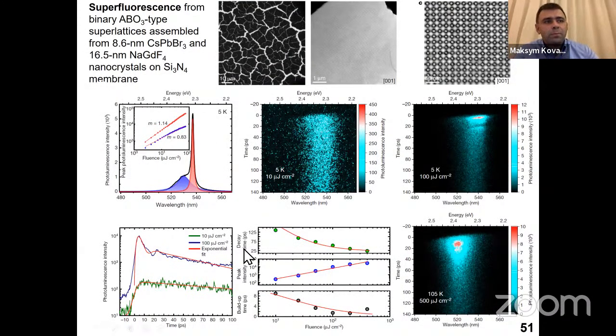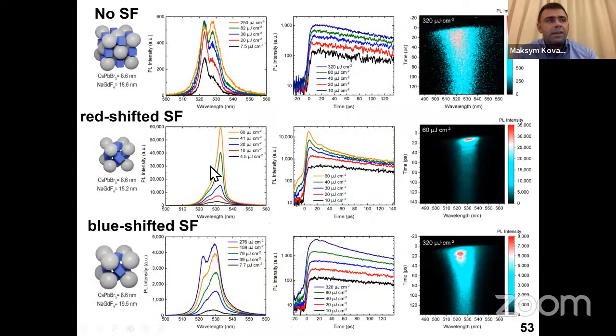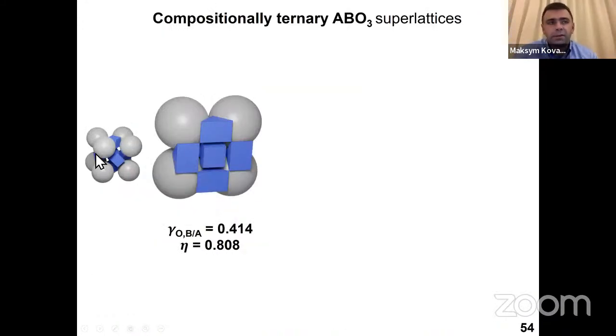And what is more interesting is that if you compare different kinds of superlattices, you start seeing correlation between the structure and the superfluorescence that you observe. For example, in one case, you even see the blue shifted superfluorescence. In another case, you see the superfluorescence threshold for the appearance as a function of the dielectric sphere diameter. And in another case, you do not observe superfluorescence because the volume fraction of these particles of perovskite you have per volume is here much smaller than in such type of a superlattice. So you start correlating your superfluorescent property with your structure.